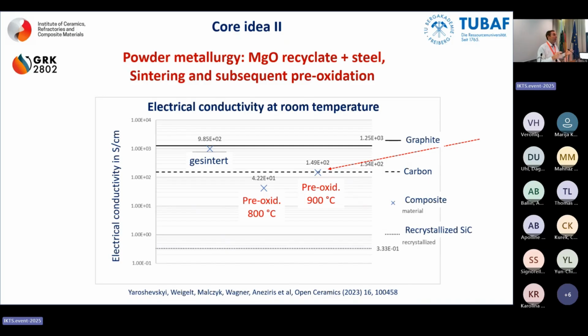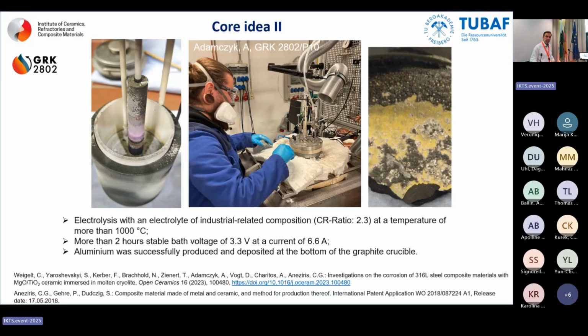Somebody would say, okay, and where is it? If you use magnesia recyclate and you use also pre-oxidation, where is your conductivity? Because you need a high electric conductivity in order to meet the demands of low energy consumption during the electrolysis. And we see here is carbon, yes? And we are in this area, well, we are not graphite, but we are in a very good area where it could work. And perhaps you can see him somewhere. Here he is, and he made with an electrode of the other guy, Serkin, they made aluminum out of it.